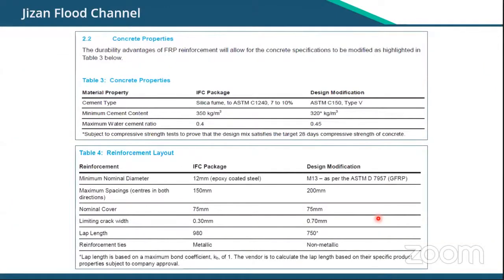So let's look at all the savings made on the project. One of the savings was related to the concrete mix. First, the water cement ratio was changed from 0.4 to 0.45, but also silica fume and some other additives were removed because they are not required for GFRP. So that was one of the savings.